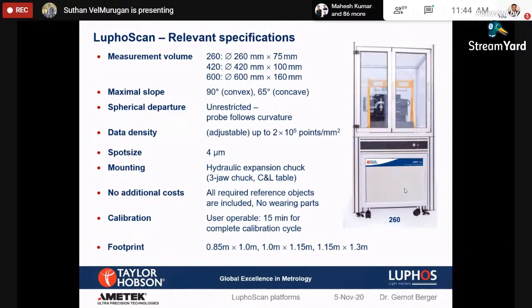So in this LUPHOScan we are mainly focusing on the form error of the optics. We are not focusing on surface roughness here. Surface roughness will be measured in the contact profiler. Here we mainly measure form error in a much faster machine. If the stylus moves, we have a limitation for the movement of the stylus. The recommended movement speed is about 1 millimeter per second.